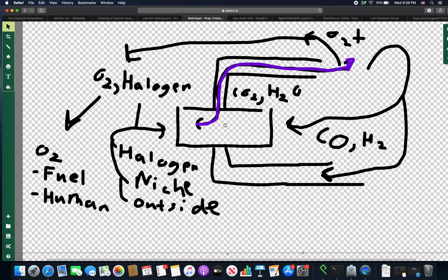Now, can we get CO2 or water on site to split it up, or hydrogen or carbon? We actually just need hydrogen and carbon monoxide. Even just carbon. Well, Mars' atmosphere is 95% CO2, and we need very little. There's also evidence of water in many different places, and methane in organic compounds, and there are some carbonates. The moon is a lot harder. There is some water, there is some carbon, but it's very low concentration in most places, so we probably have to bring it along with ourselves and seal the whole container more.